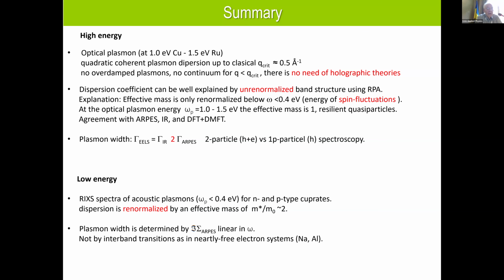And the dispersion coefficients can be well explained by an unrenormalized band structure using an RPA approximation. And the mass enhancement is only seen below 0.4 eV, because there we have a renormalized band structure, probably due to a coupling to spin fluctuation, but at higher energy, the optical plasmons are not renormalized because the effective mass is close to 1. And the width is roughly twice the scattering rate measured in ARPES, which is the same as in optical spectroscopy. It's roughly a factor of 2 of the ARPES scattering rate. So this relates in some ways a 2-particle spectroscopy with a 1-particle spectroscopy.